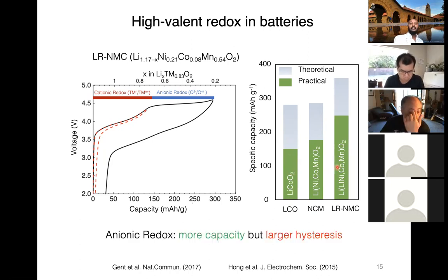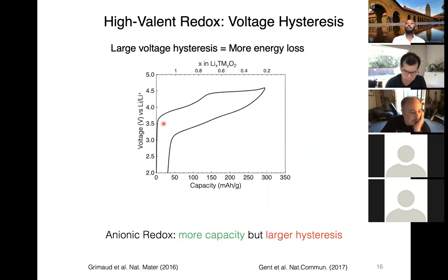The second difference is that the gap between the forward and the reverse process, which we call hysteresis, is larger for lithium-rich NMC, shown in black, as opposed to lithium cobalt oxide. Therefore, this anionic redox mechanism is allowing us to improve the capacity as shown on this curve, but it comes with a cost, and that cost is there is large hysteresis and there's a huge gap between the forward and the reverse process. What this gap means is we are having a source of energy loss.